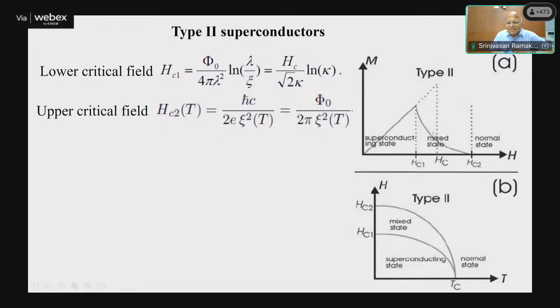And then in the mixed phase, you will have a field greater than Hc1, and the thermodynamic field Hc has no physical significance in this state in a type 2 superconductor. Then you have Hc2, which is the upper critical field, and this is the lower critical field. The upper critical field is related by phi naught over 2 pi xi squared.